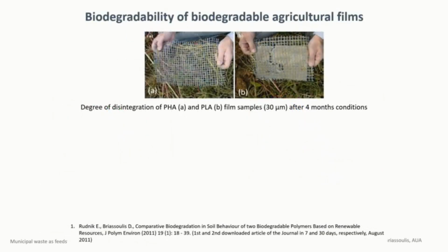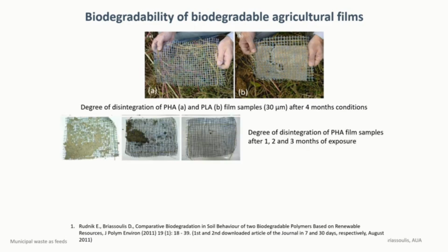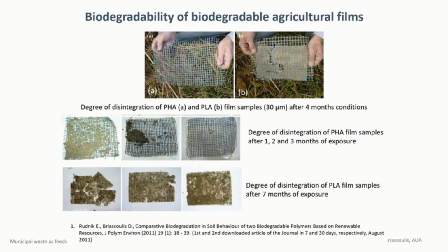You see here a comparison of a PHA-based emulsion film with PLA film, 30 microns thick, after 4 months of exposure. Here you see the PHA-based film in 1 to 3 months of exposure in the soil, and the corresponding picture of PLA film after 7 months of exposure, which is not biodegradable in soil.